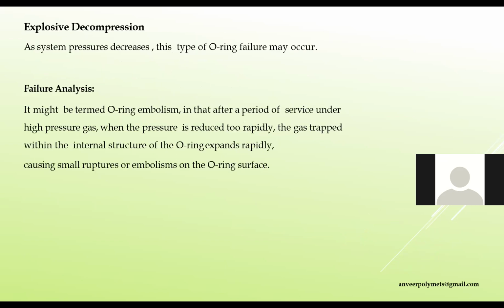Then explosive decompression. As the system pressure decreases, this type of failure may occur. Explosive decompression is also termed O-ring embolism. In this, after a period of service under high pressure, when we reduce the pressure too rapidly, the gas trapped within the internal structure of the O-ring expands, which leads to small ruptures or embolisms in the O-ring surface, and that rupture causes failure in the application of the seal.